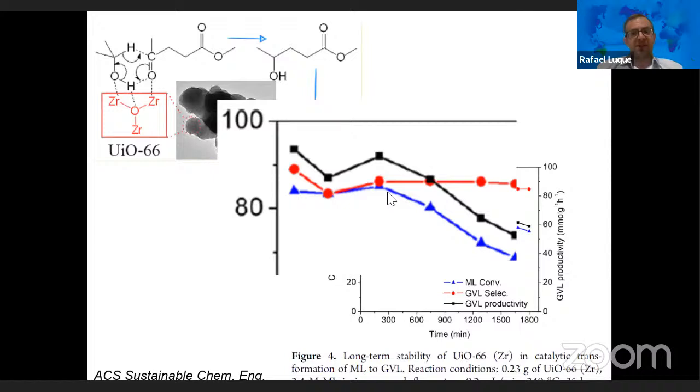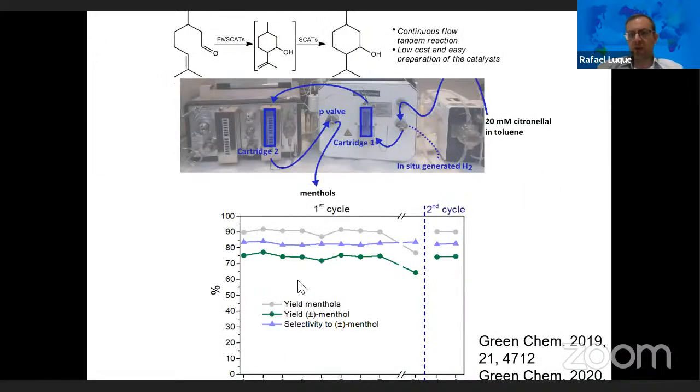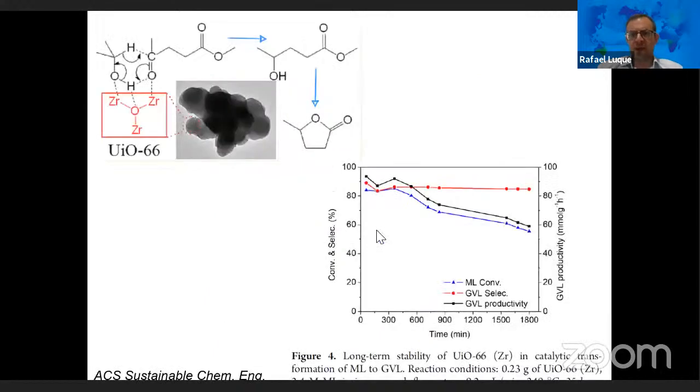But if you leave it for a longer reaction time, you find out that the material deactivates. So if you stop at this point, you will say the materials are highly stable. My recommendation, of course, and take-home message, is to at least run a long-term stability run of 24 hours to definitely confirm that the material is nicely active and stable, such as in the example below that you're seeing here: 24 hours plus a second cycle.